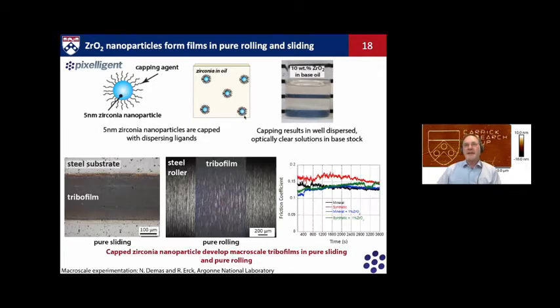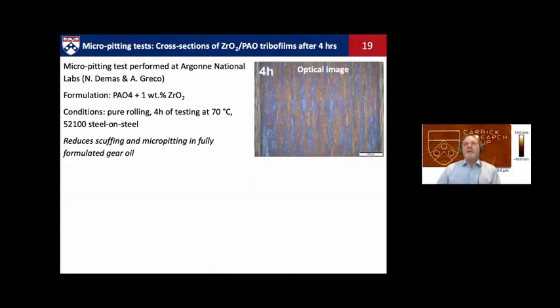The solutions stay clear. And in these results from Argonne Labs from Nick Demas, if you slide in a reciprocating rig or a micropitting rig, you see tribofilms, and you see friction that's pretty comparable to the base oil. It's not much higher, it's not much lower. But they do see that you get films on the surface, and they have verified that these zirconia tribofilms will actually reduce scuffing and micropitting compared to a fully formulated gear oil.